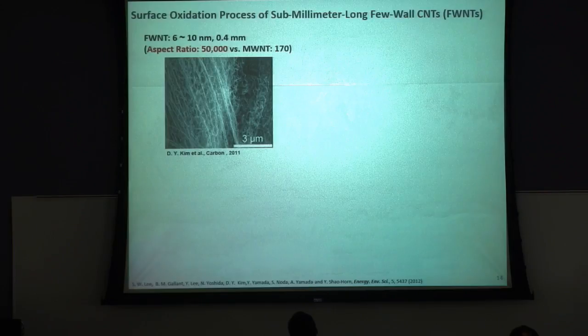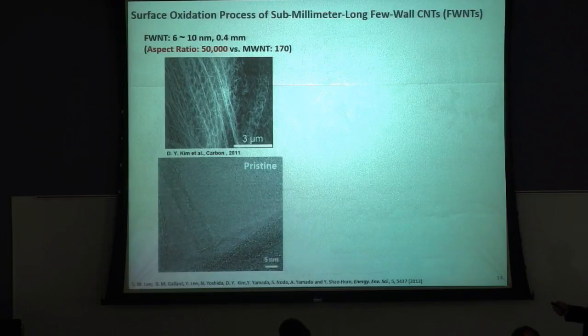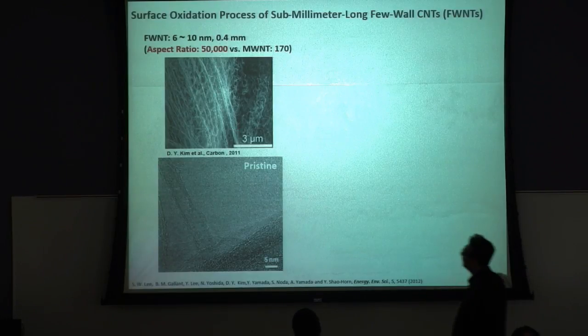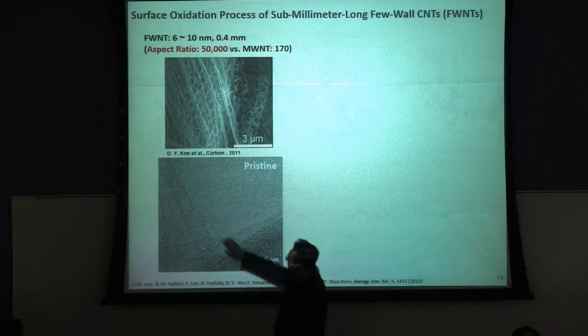For this experiment, we used few-walled carbon nanotubes. The average wall number is around 3 to 4, the diameter is 6 to 10 nanometers, and the length is 0.4 millimeter. It's pretty long, actually. The aspect ratio is around 50,000. This is the pristine few-walled carbon nanotube, and in this image we can see the wall number is on average 3 to 4.